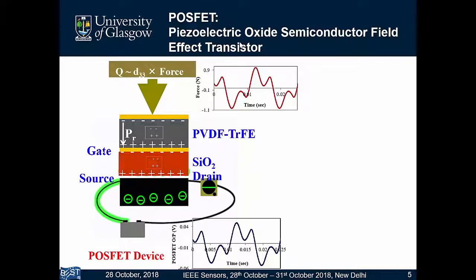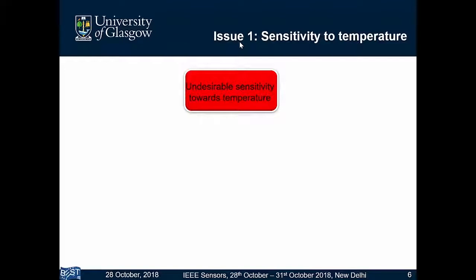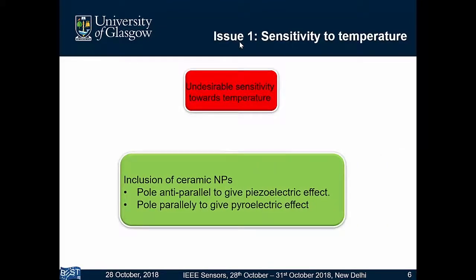So if my finger is hot, if I have a fever, and I touch my sensor, then it will respond to both my force as well as the heat of the body, which is a kind of noise, because sometimes we don't want sensitivity toward temperature. So the first issue was sensitivity to temperature, and this has been recently published in IEEE Sensors Journal. In this work, we used nanoparticles of barium titanate.